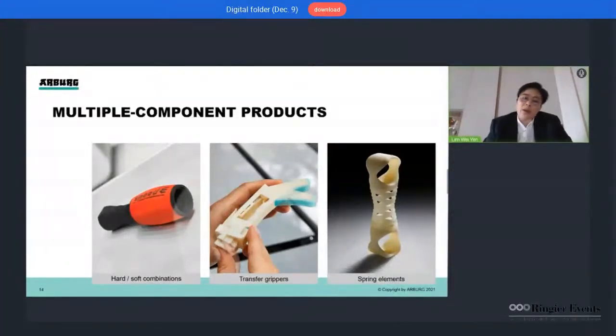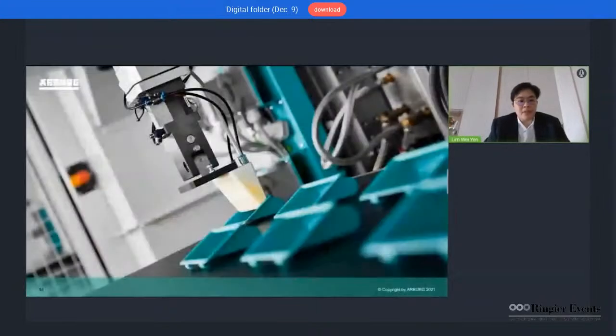So for hard-soft combination, we are able to print housings as well, hard-soft housings like this over here, and spring elements that are used in cycling. So as you can see here, printing with two materials opens up the possibility for further design capabilities, and does not restrict the users from thinking additive. So as you can see here, this is also a two-component part that demonstrates a great value that we can obtain by combining two materials, in this case, a hard-soft material.